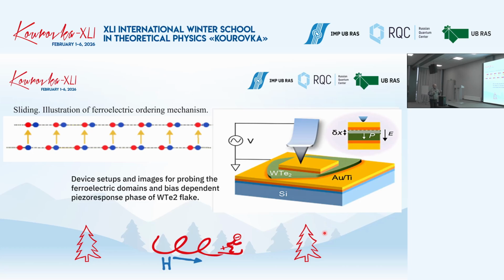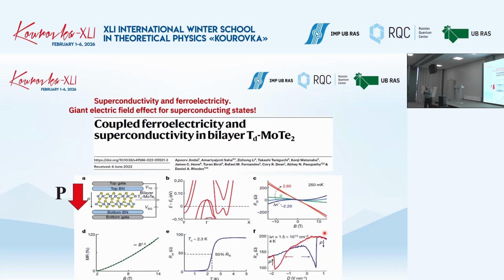Experimentally, this kind of unusual ferroelectric ordering can be measured, for instance, using some probe techniques like it is shown here for tungsten telluride. A sort of piezo response they measured and observed ferroelectric domains. And so it looks like this kind of phenomenon does really exist. And let's see now what happens with superconductivity.